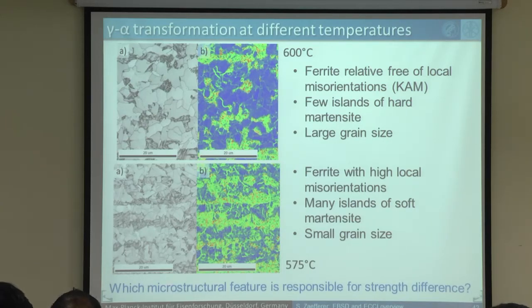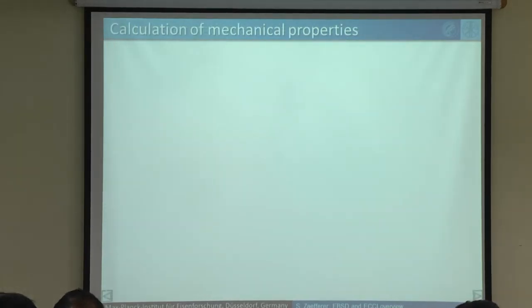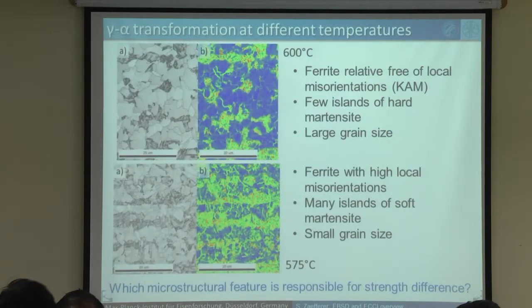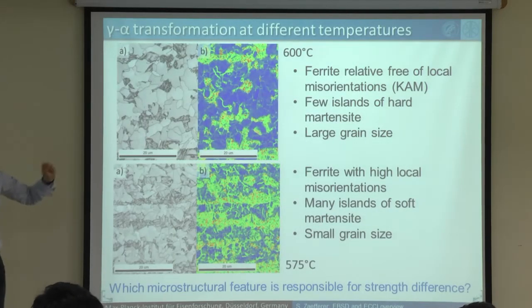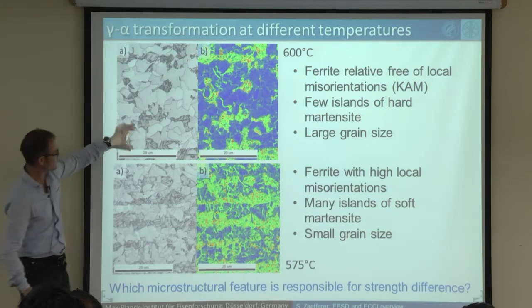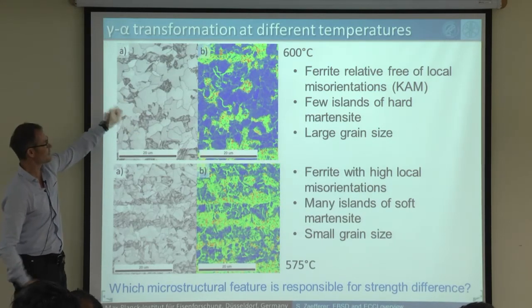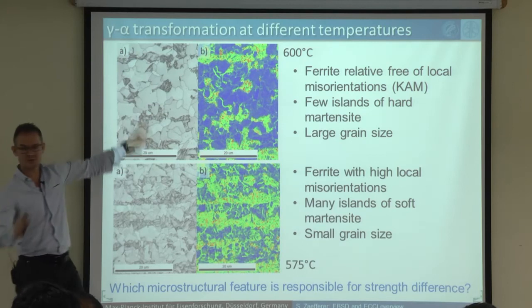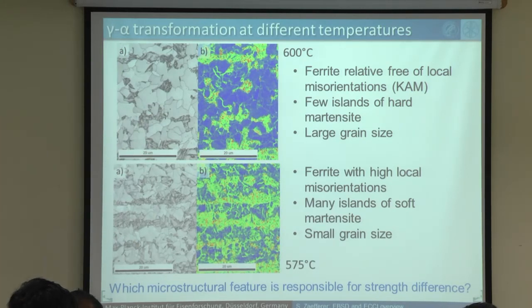So which of these differences, grain size, dislocation densities, so KAM densities, martensite hard or soft, which of these differences is responsible for making this peak in strength? And this you can figure out by calculating now. So you take EBSD. I said EBSD is a quantification technique. You quantify grain size, you quantify martensite grain size, you quantify martensite volume fraction, you quantify dislocation densities, and now you take all these numbers and you go into a calculation.